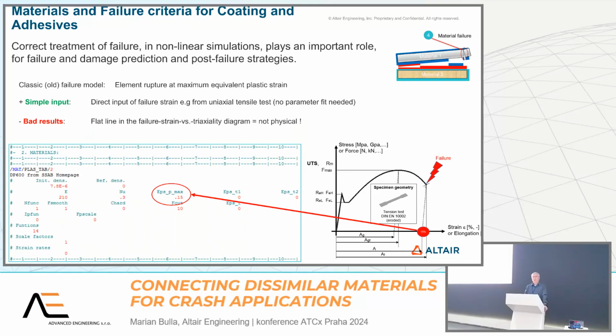Okay, for getting the material card, you do this tensile test, which is the first approach you did for fracture in the past. So this beautiful fracture limit was obtained or put in the material card here, Radioss or LS-DYNA or PAM-CRASH, all the same, and people were happy. So the maximum plastic strain was added to the material card, and it failed once this plastic strain limit was reached. Very nice, beautiful, simple to use. You need one test and you input your value directly from the test.